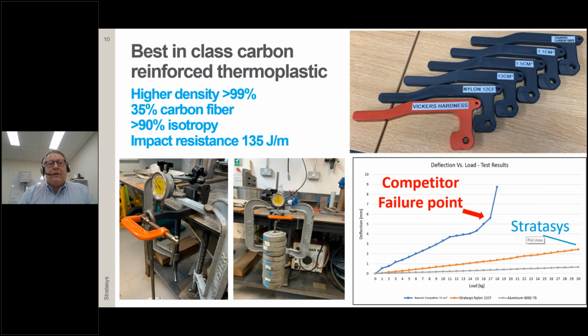A quick one on the nylon carbon fiber again, because this is very often my choice of material when I come to shop floor tooling. We have right now, or by today, the best in-class carbon fiber reinforced thermoplastic. We have a much higher density, up to 99%. We have 35% chopped carbon fiber placements. We are achieving almost a 90% isotropy consistency. And we have with 135 joule per meter actually a fantastic impact resistance.